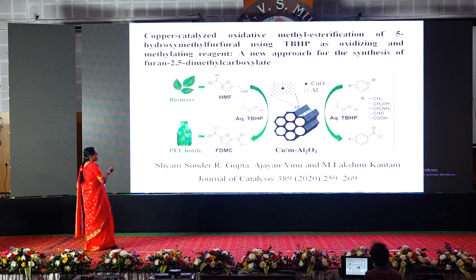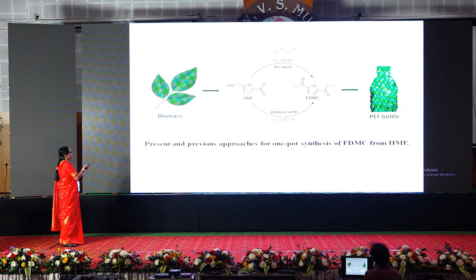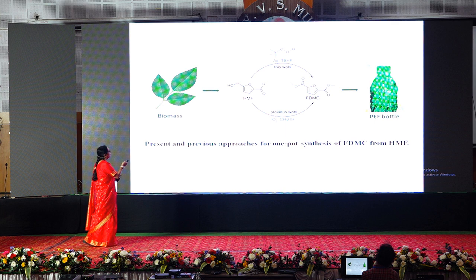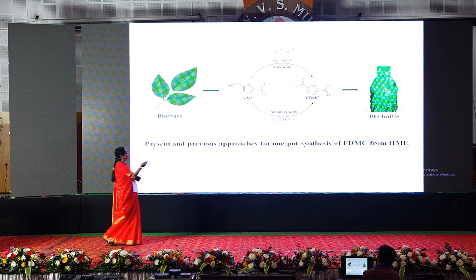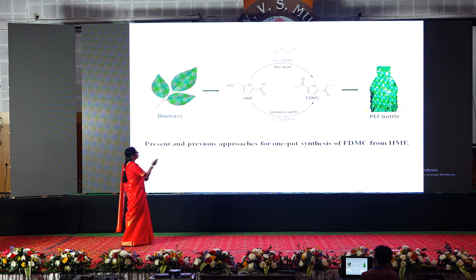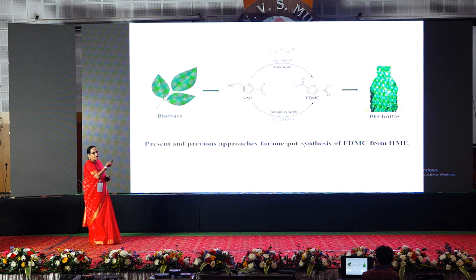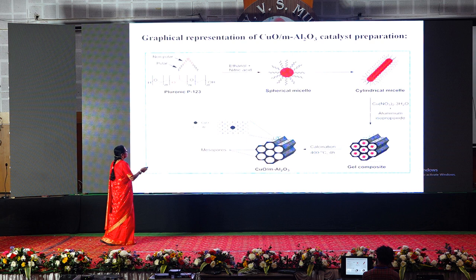And here what we did is, you can see this one, again, we want to make the PEF bottle, and you want to make this reaction to make the furan dimethyl carboxylate. You want to use TBHP and methanol with hydroxymethyl furfural. And what we did is we have taken the tertiary butyl hydrogen peroxide, and with our catalyst, it can act as a methylating agent as well as an oxidizing agent. So you can make this one very easily.